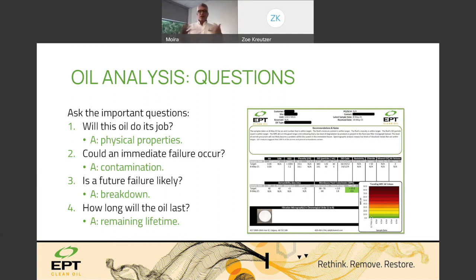So looking at, could an immediate failure occur? Two things I look at there. I look at viscosity, I look at physical contamination, and then I look at things like additive levels. And if your oil has no additives in it, right now the condemning limit for a lubricant is when the additives are less than 25% of the new value in combination with a 300% increase in acid number.